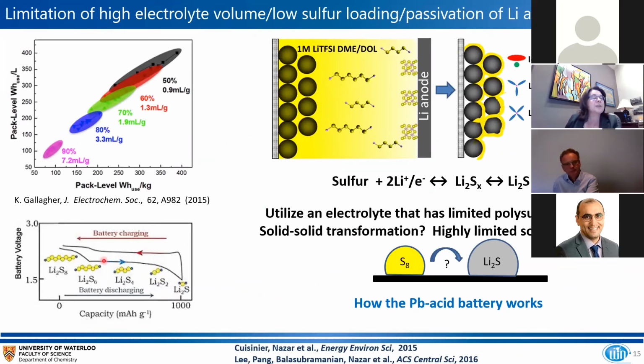So as I mentioned, the polysulfides that are formed in solution go through this cascade all the way from the most oxidized to the most reduced member. And in typical solvents, which are dimethoxyethane and dioxolane, they are very highly soluble. And as they form, if they're not constrained in some fashion at the cathode, which is what that sheath of carbon did, they drift over and, as I said, reduce on the surface of the anode and effectively passivate it and shut the cell down.